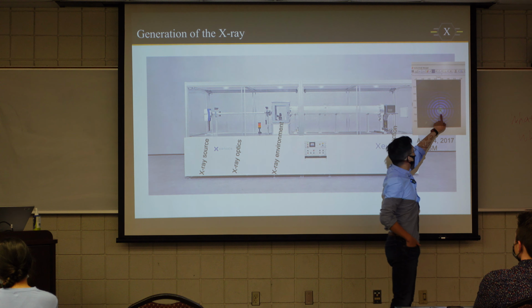The largest Q is defined by how close we can move the detector and how wide our detectors are. In our setup, we can go up to about, I think, 40 to 50 degree angle, and this translates to really large Q. In the next slides, this gives you an idea of the Q range we can measure at different sample-to-detector distances, the SDD, meaning how far you move your detector from your sample.